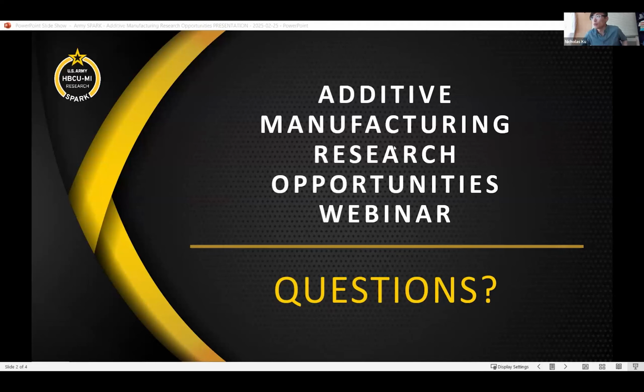Here in the ceramics branch, we are mainly ceramists, so my organic chemistry background is pretty poor. What I would say is we've been using commercial off-the-shelf polymer binders to create our suspensions for direct ink writing. In terms of binder jetting, we have an X1 binder jet. We've been using what they commercially provide as binder systems, but fine-tuning the binder and polymer chemistries to increase green strength, increase dispersion, or tune rheology is definitely something we're interested in.